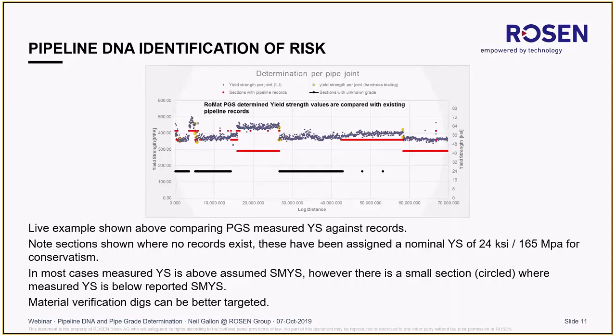Here we have a similar graph, but we compare the measured yield strength against the records. The solid red and black lines are what the operator's records stated their SMYS was. You can see that in most cases, the measured yield strength is above the operator's assumed SMYS. You can also see there are areas of black lines which have a SMYS of 24 KSI. Again, this was an American line, and the regulations there determine that if you don't know the grade of a pipeline, you have to assume a yield strength of 24 KSI. One of the benefits of this service is that it has shown that even where they didn't have records, the population appears to be very similar to areas where they do have records.